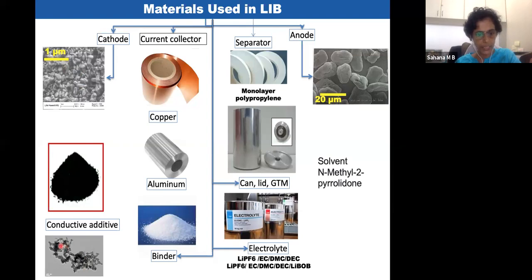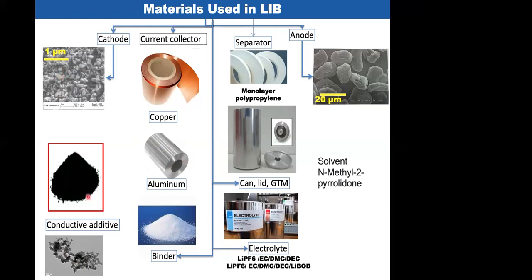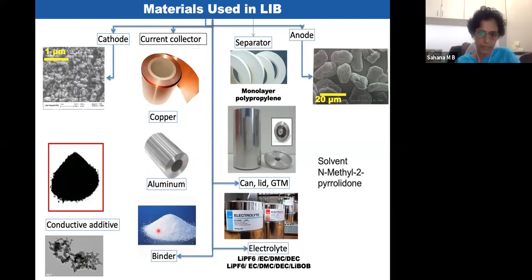So if you magnify that, it looks like this. Now these materials are coated over the current collector aluminum foils. Now these are all powders, whether it is carbon black or LiFePO4. So we need something to bind them together. That is a binder. And again, this is also a solid. So what we need to do is dissolve this binder in the solvent here. You can see to the right hand side, the solvent is N-methyl-2-pyrrolidone. We call it shortly NMP. These three things are mixed together and coated over the current collector, aluminum.